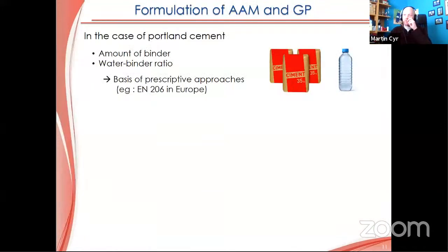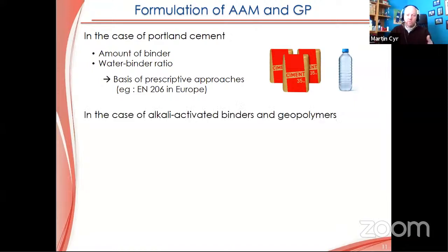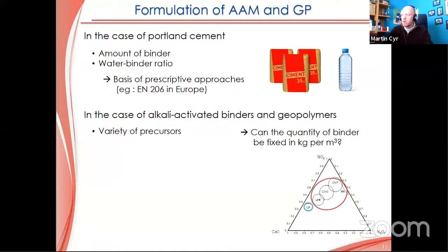So if we want to make the formulation, usually there are the prescriptive approaches we find in the world. For instance, EN206 in Europe, we fix the amount of binder, we fix the water binder ratio, and the industrial partners are very comfortable with that. But when we want to do something else, in the case of other kinds of binders, such as alkali activated binders and geopolymers, of course, we have the variety of the precursor. Can the quantity of binder be fixed in kilogram per cubic meter? Probably not. It's not so easy to do that. Where do we count the activator itself? So that's a lot of questions we usually get from our industrial partners.